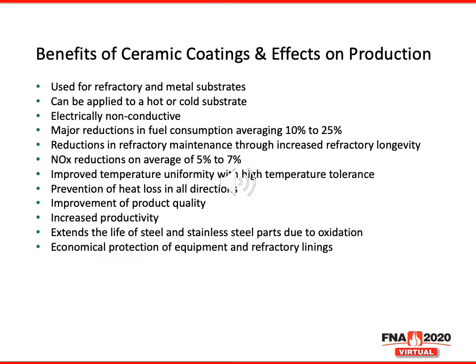With the coatings being applied to the entire hot face lining of a furnace, there is prevention of heat loss in all directions. With this prevention of heat loss in all directions comes improvement of product quality through the reduction of cold spots. With the increased amount of heat available, there can be an increase in productivity, as we will see later on in this presentation. The coatings will increase the life of stainless and steel parts by reducing oxidation at high temperatures. And based on their price, they are an economical means of protection of equipment and refractory linings.